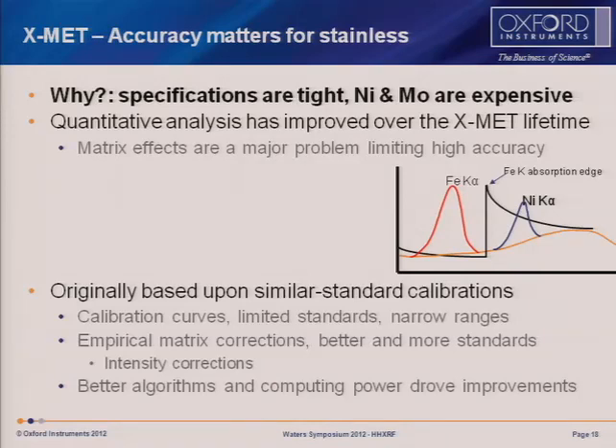And another one sits between chromium and iron. So nickel gets very strongly absorbed by iron and by chromium. And similarly, iron gets absorbed by chromium. And all of these interelement effects mean that if you're to just do a simple calibration, you can readily be 10% inaccurate, and much worse in some cases.